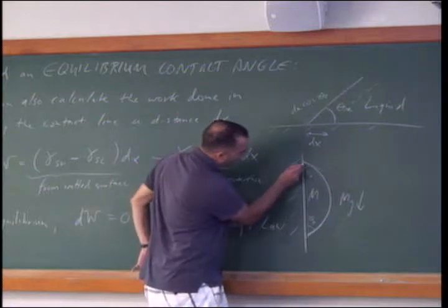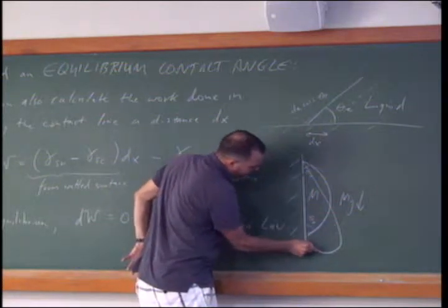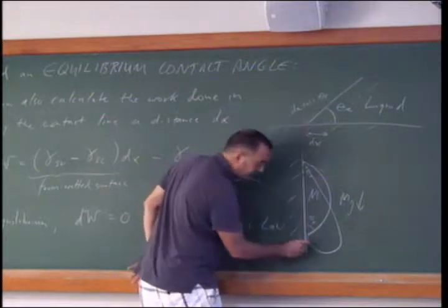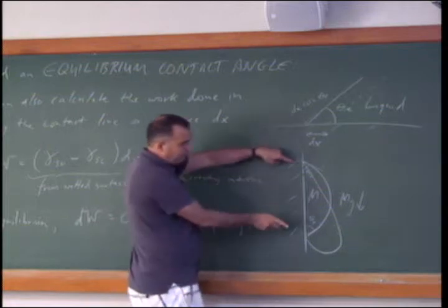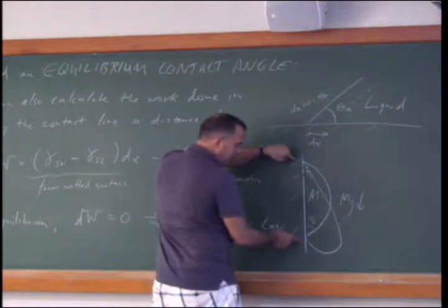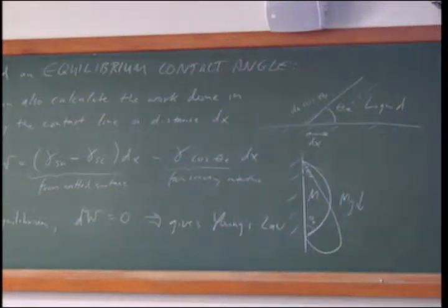But now we have the situation where the drop actually looks like this, or can look like this, where this is now the retreating angle, this is the advancing angle, and you can still have a static situation. So then the net force you get by integrating the tensile force around the contact line, and you see that this contact angle hysteresis can support the weight of small drops. So that's what we just saw there, and we can see it again. And of course, there's going to be a size at which it doesn't work anymore. So here there will be a critical angle, and this is how you can measure the contact angle hysteresis, right? Basically know the size of your drop, and you measure the angle at which the thing starts moving.